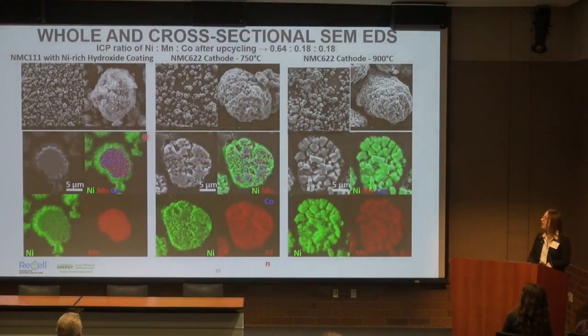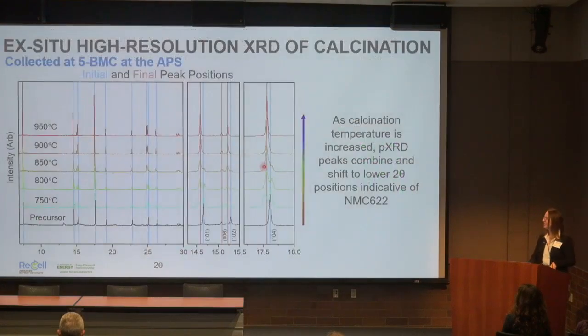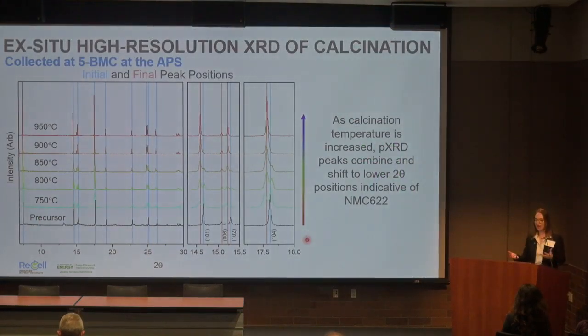So here are some of the SEM images of the upcycled cathode material. We can see our precursor material with our end-of-life cathode material in the center with our nickel-rich shell on the outside. We can see that we retain that spherical secondary particle agglomerated morphology. And then at higher temperatures, we can see the diffusion of the nickel-rich shell into the bulk composition. I won't show too much data on this. I don't want to go too technical, but we basically create a single phase, looking at crystalline data with X-ray diffraction. Here's the precursor material with a shifted peak indicative of a lower nickel cathode, down to a single peak at a higher nickel cathode.